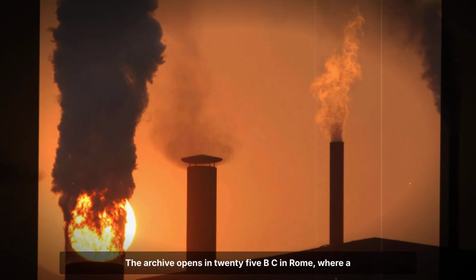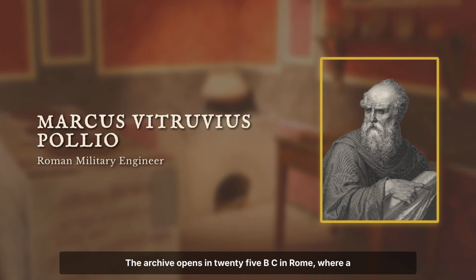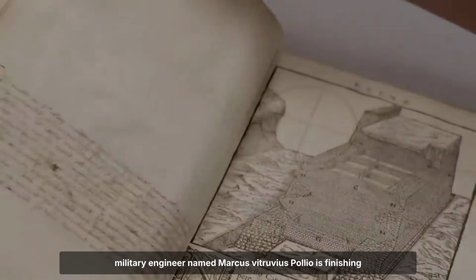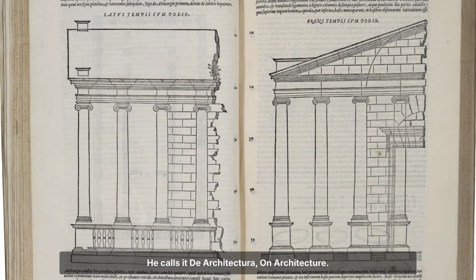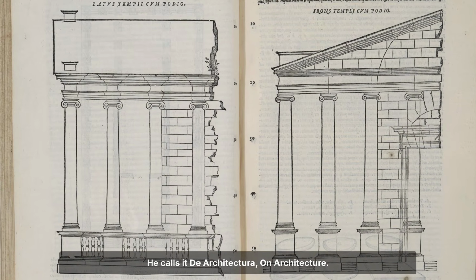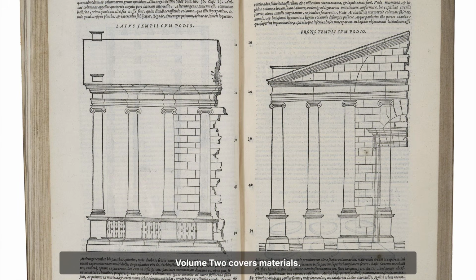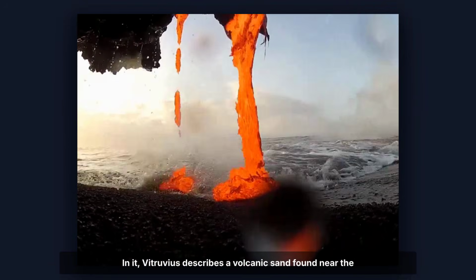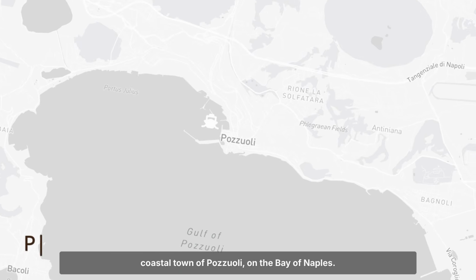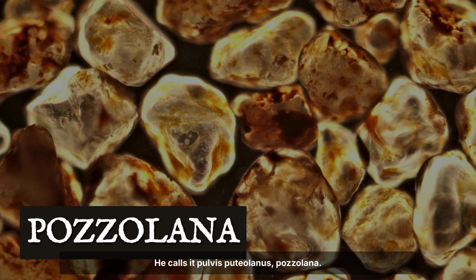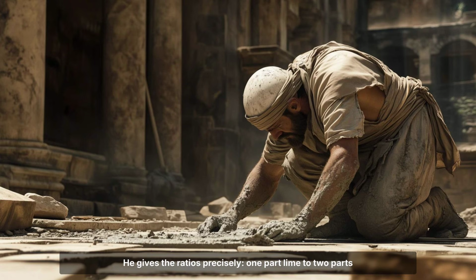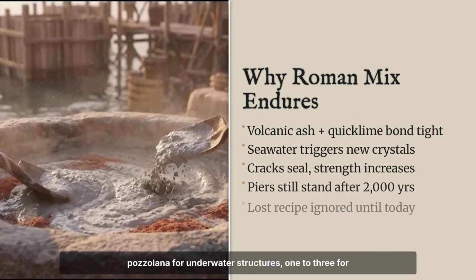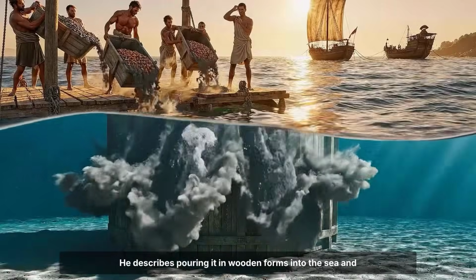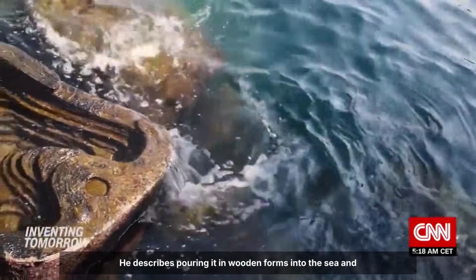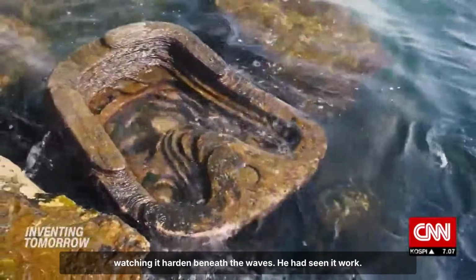The archive opens in 25 BC in Rome, where a military engineer named Marcus Vitruvius Pollio is finishing a 10-volume treatise for the Emperor Augustus. He calls it De Architectura, on architecture. Volume 2 covers materials. In it, Vitruvius describes a volcanic sand found near the coastal town of Pozzuoli, on the Bay of Naples. He calls it pulvis putiolanus pozzolana. He gives the ratios precisely: 1 part lime to 2 parts pozzolana for underwater structures, 1 to 3 for buildings on land. He describes pouring it in wooden forms into the sea and watching it harden beneath the waves. He had seen it work.